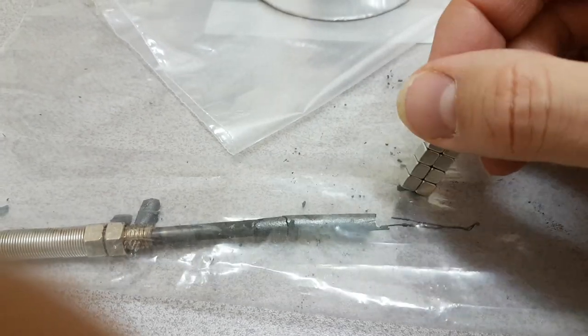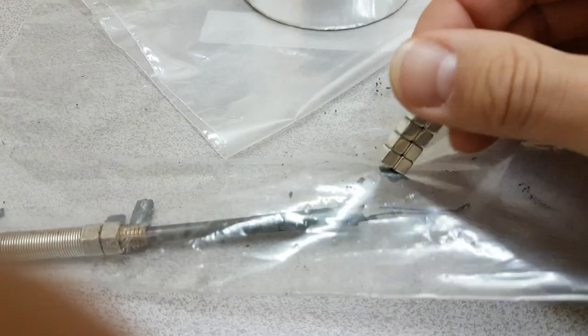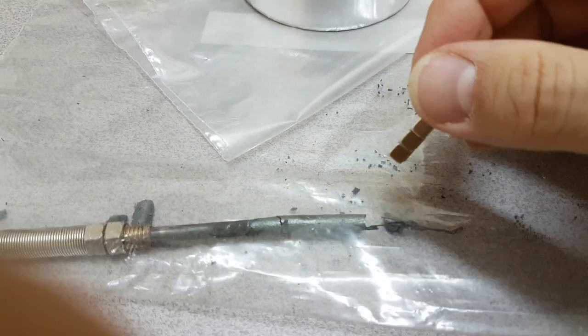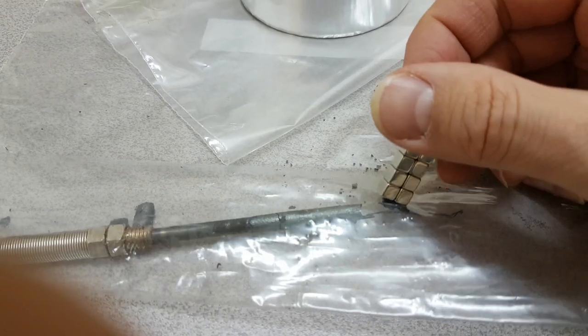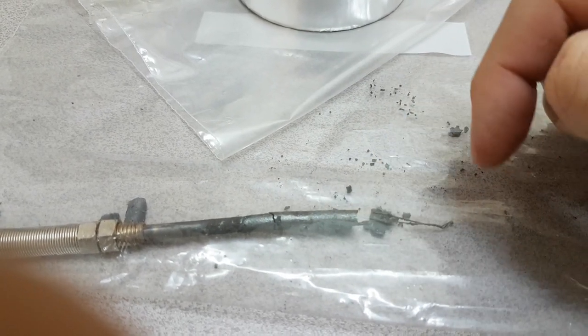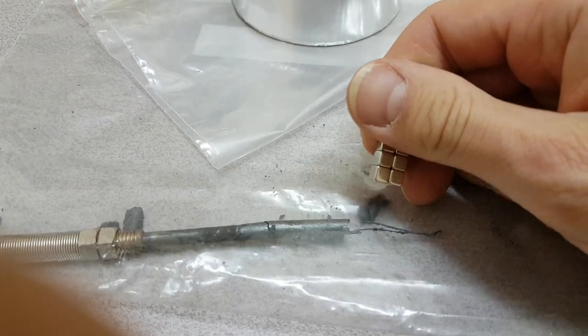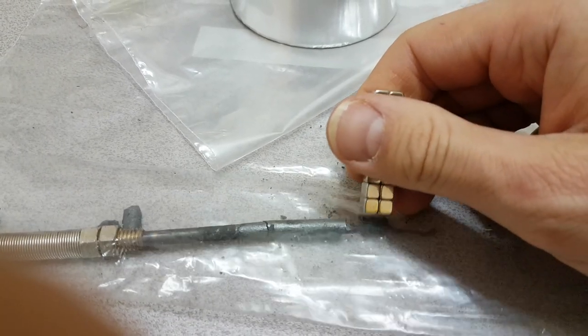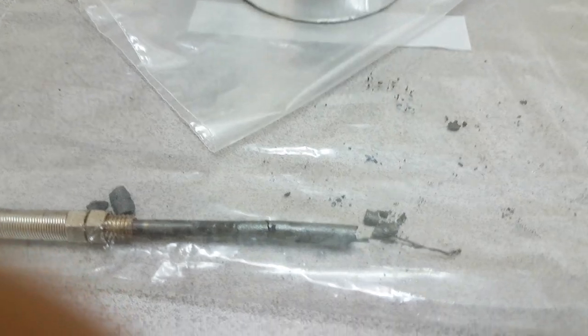As we thought, it looked like ferrite crystals, and ferrite crystals are magnetic. This will hold the magnetism now. I imagine if I put a magnet from this camera on there, these pieces would be highly magnetized. So that's the nature of it — it has converted from something that's non-magnetic stainless steel to something that is magnetic.